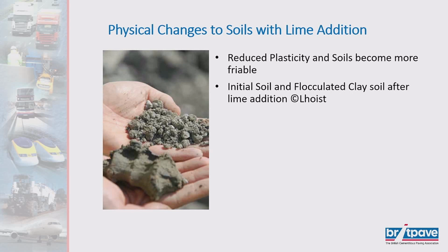And what that looks like, rather than as a science lesson, is effectively you're going from a nice mouldable clay at the bottom, which is nice and wet. That exchange causes a flocculated clay. It acts slightly more granular in nature. And part of that physical change with the lime is that if you were to add a cement or other hydraulic binder to that, it's very difficult for it to mix in. Once you've flocculated that material, it is then very readily acceptable to cements and other binders to get a very high strength addition. Lime doesn't purely just dry the soil out.